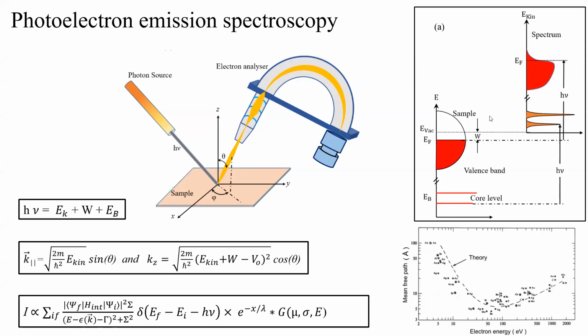Now, close to the Fermi energy, if this is the valence band of the sample that I'm trying to study, and this is the Fermi energy, it means all the states below this are filled. At finite temperature, I will have a Fermi-Dirac distribution which goes like this. And when I'm trying to measure it with photoelectron emission spectroscopy, I will get the effect of Gaussian broadening due to the spectrometer, and hence a convolution of the valence band spectrum at finite temperature and a Gaussian function, with sigma value basically the resolution of the detector. Because of these two effects, we get this type of feature in place of this feature.